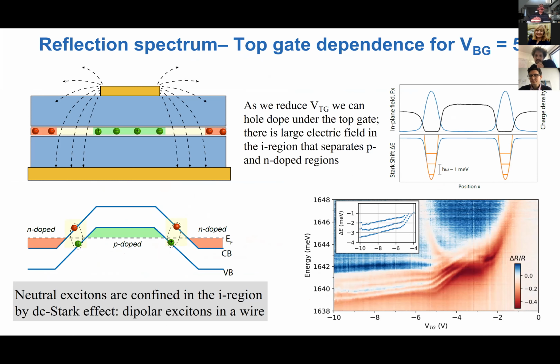Yeah, that's an interesting question. I don't know. I think it would definitely be interesting to explore this regime. Of course, even though the lifetime of these excitons is longer, based on the line widths, we measure line widths as narrow as 0.1, 0.2 milli-electron volts, which is almost unheard of for TMDs. So the lifetime has been prolonged, and that's something you would expect because this collective enhancement effect is suppressed. But still, it's a short lifetime. On the one hand, we expect interactions to be strong, but excitons are dissipative. So what exactly does this mean for predictions based on 1D physics? There is definitely interesting physics out there.